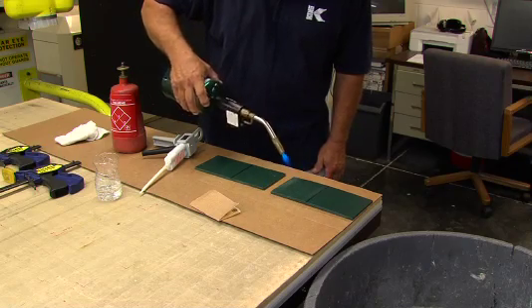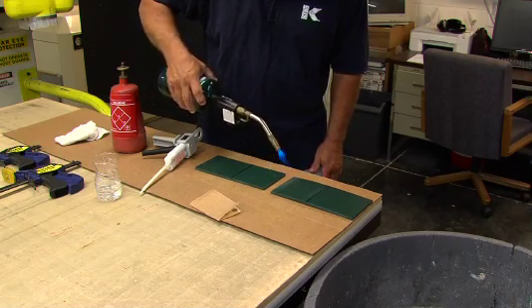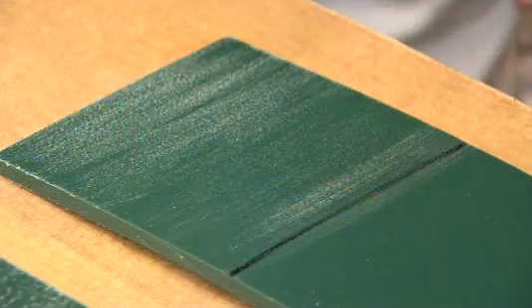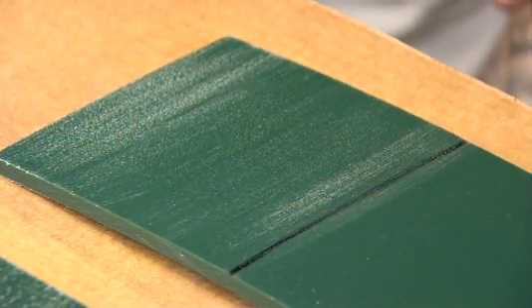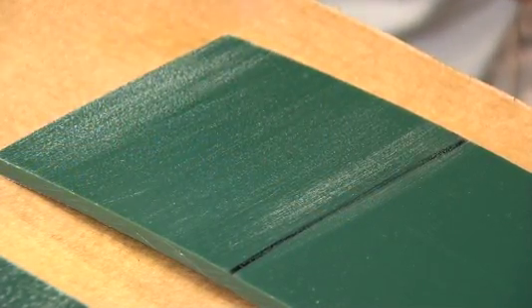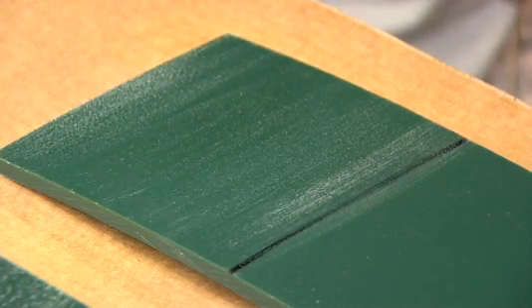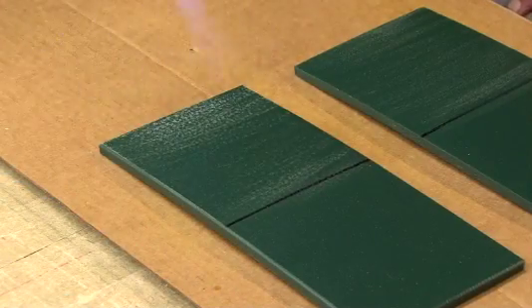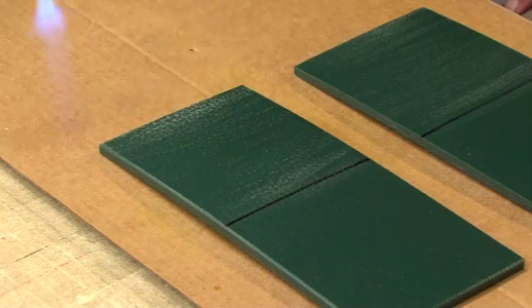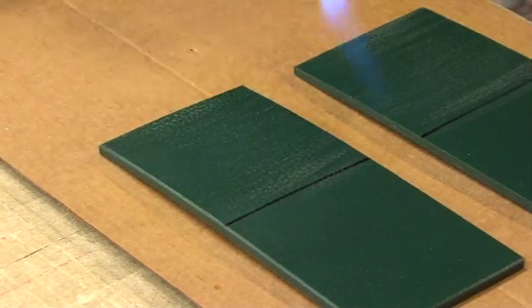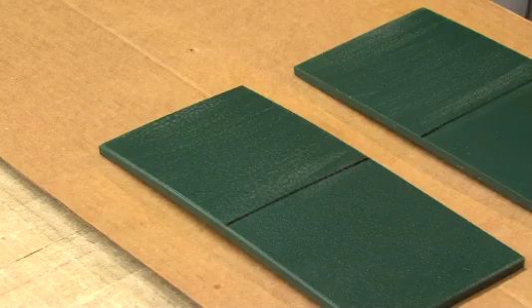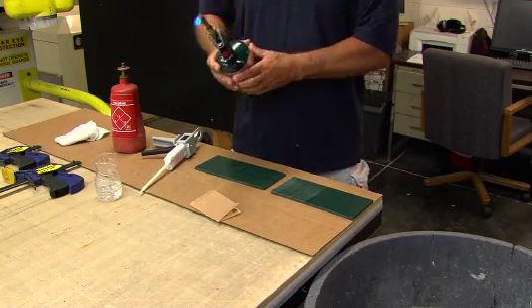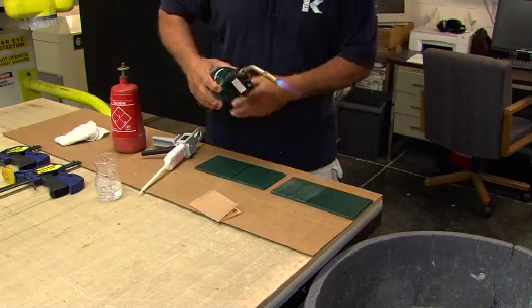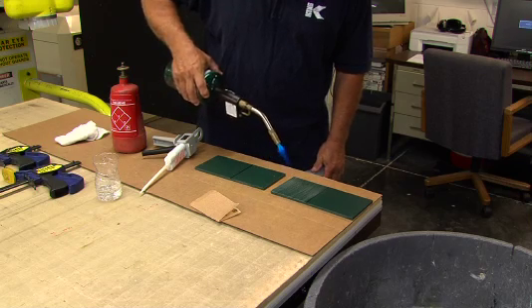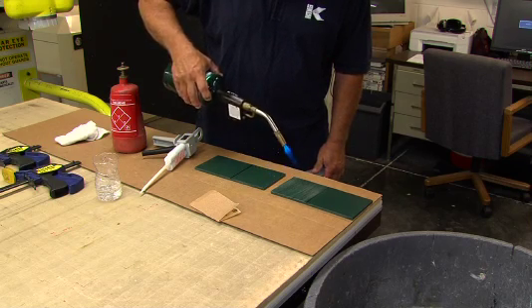Working in a safe and well-ventilated area, hold the torch so the flame is approximately 1 to 2 inches or 2.5 to 5 centimeters away, and the blue oxidizing portion of the flame is on the StarBoard surface to be bonded. Pass the flame over the surface at a rate of approximately 12 inches or 30 centimeters per 3 seconds. For this example, the total time the material should be exposed to the flame should be 2 to 3 seconds, about 1/2 second per stroke.